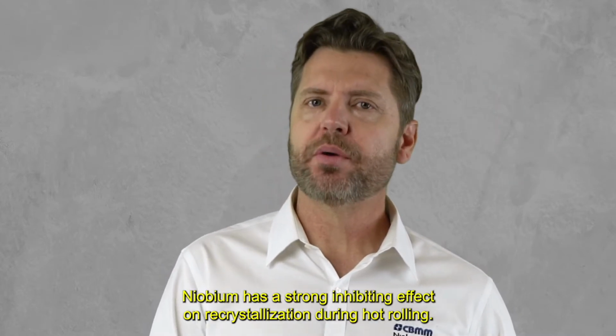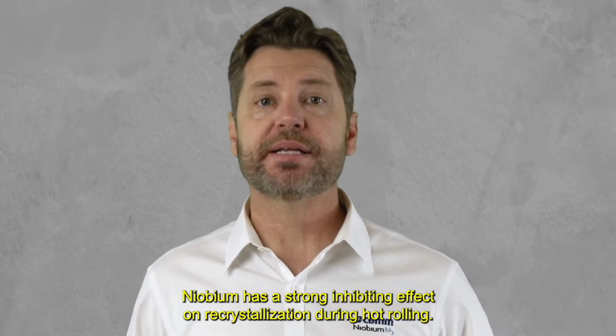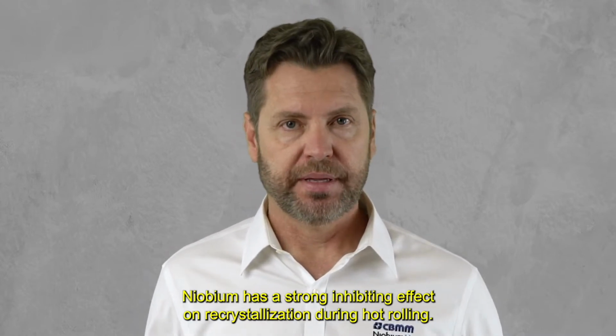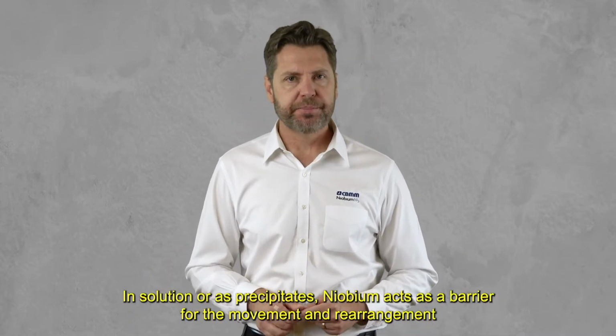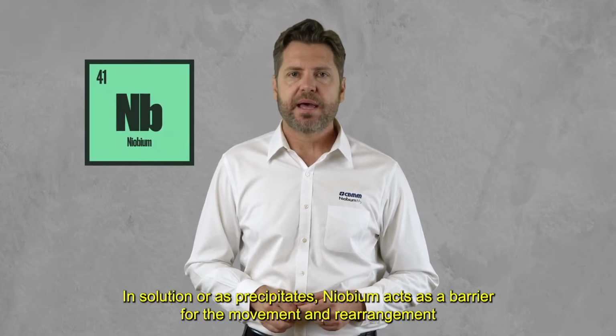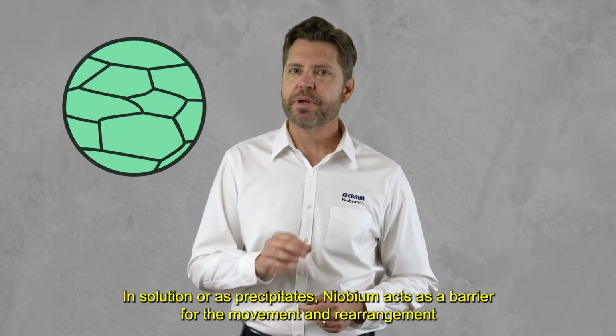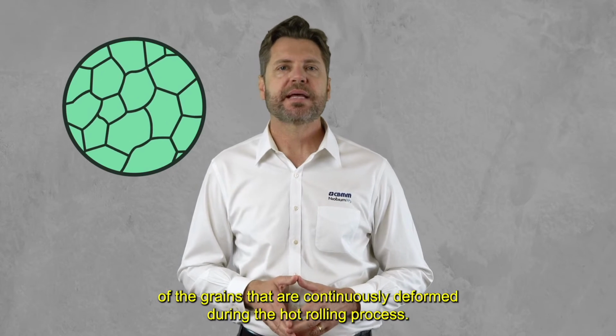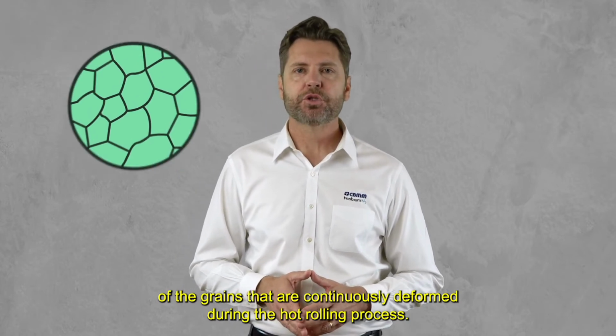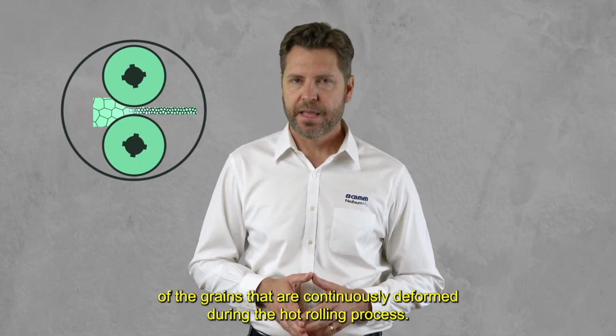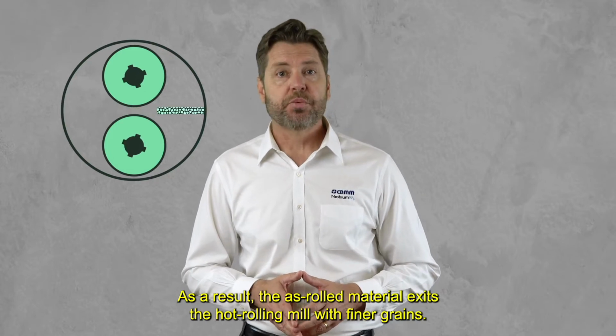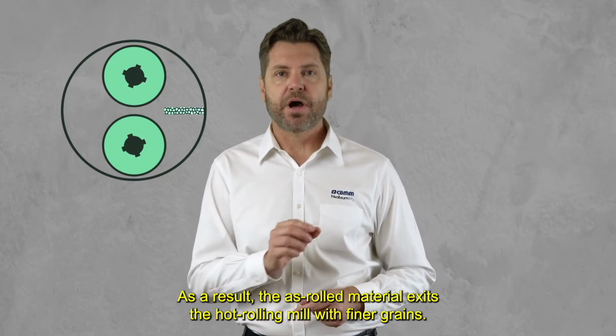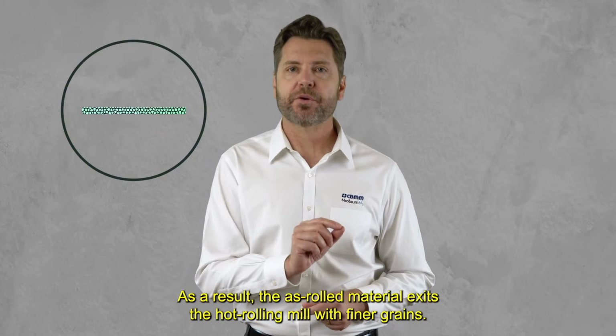Niobium has a strong inhibiting effect on recrystallization during hot rolling. In solution or as precipitates, niobium acts as a barrier for the movement and rearrangement of the grains that are continuously deformed during the hot rolling process. As a result, the rolled material exits the hot rolling mill with finer grains.